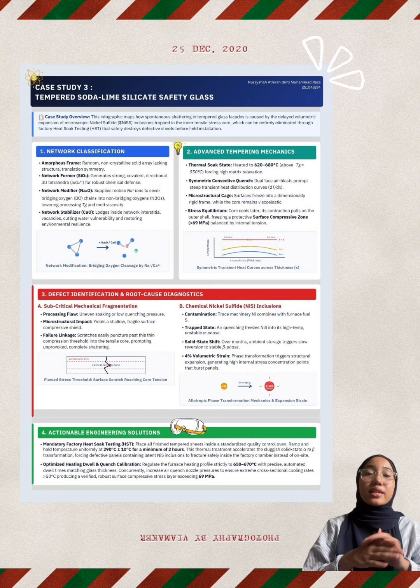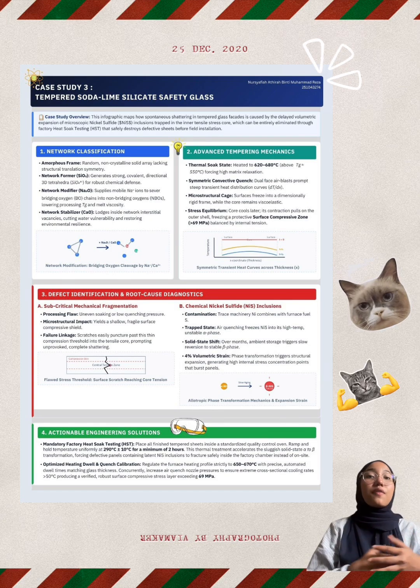Alright, so glass starts as an amorphous frame, a random, non-crystalline array. We use silicon dioxide as our network former to build strong, covalent 3D tetrahedra for chemical defense. We also add sodium oxide as a network modifier to lower processing temperatures and melt viscosity. Finally, we add calcium oxide as a stabilizer to cut down water vulnerability and restore environmental resilience.